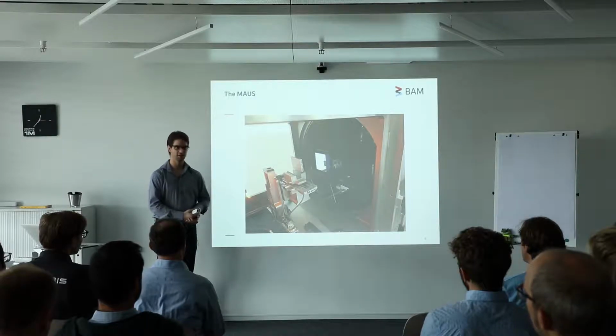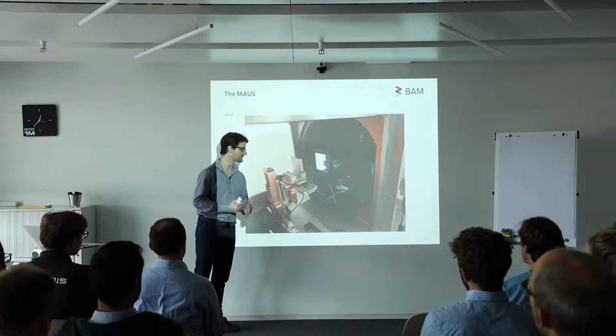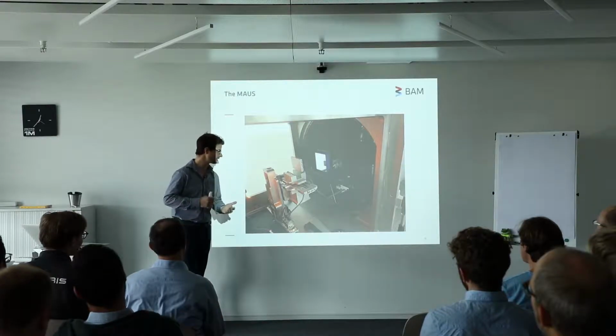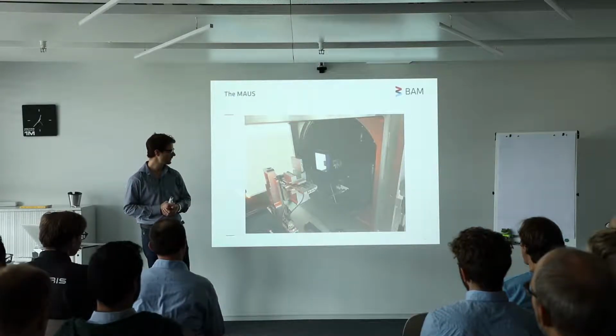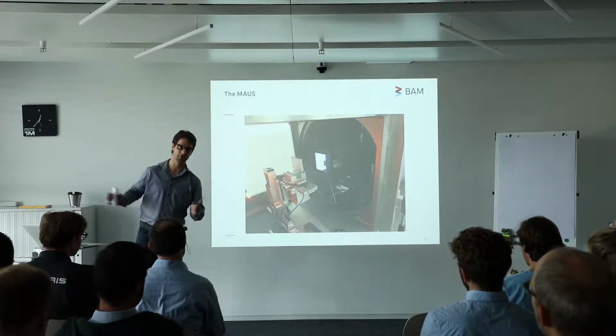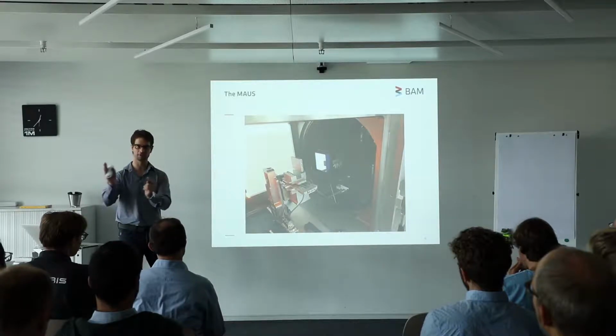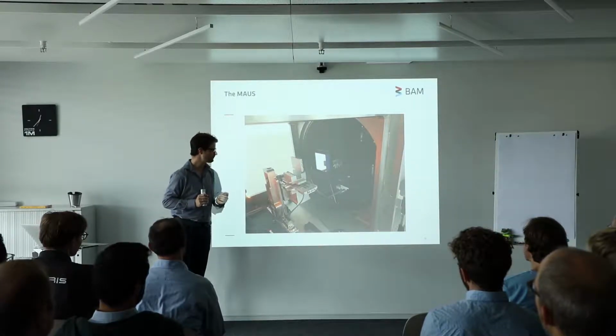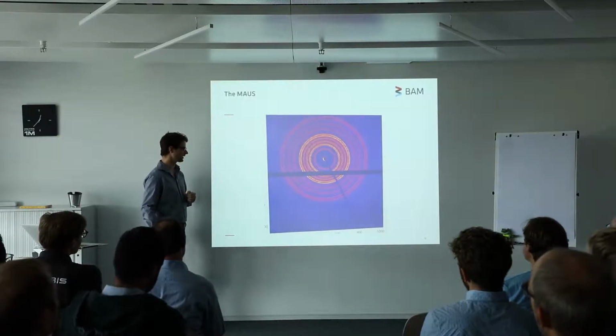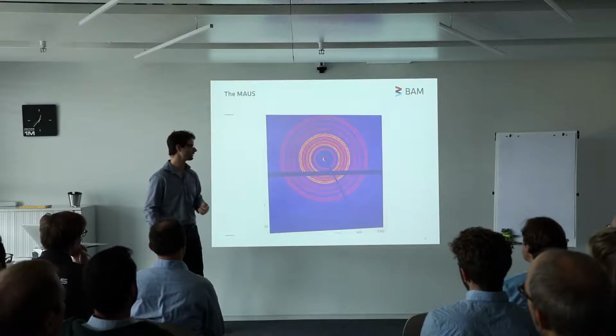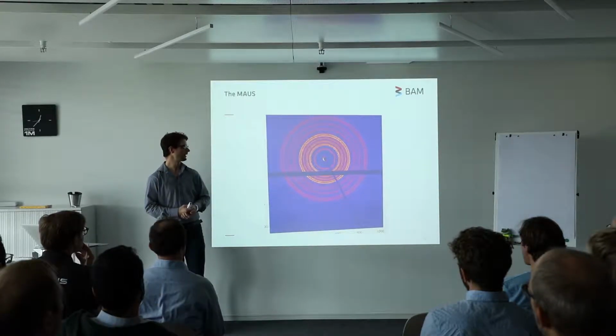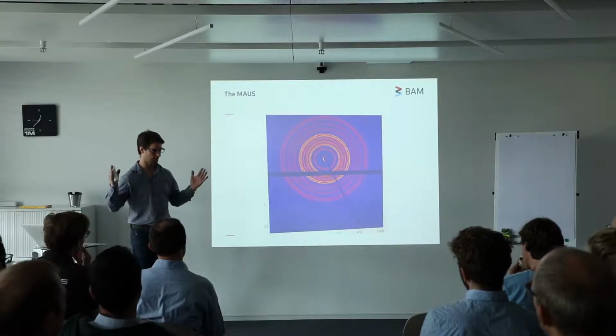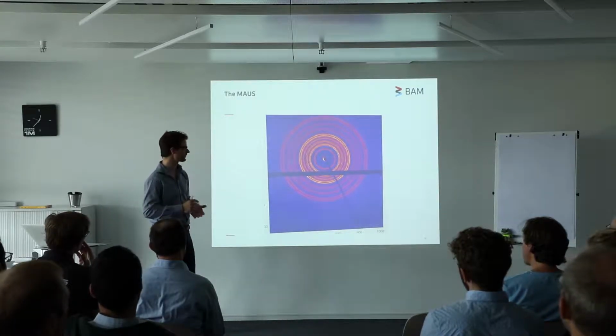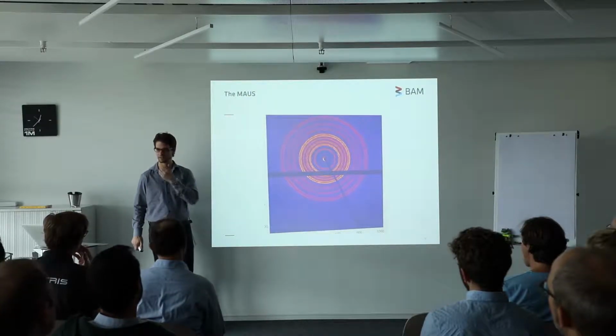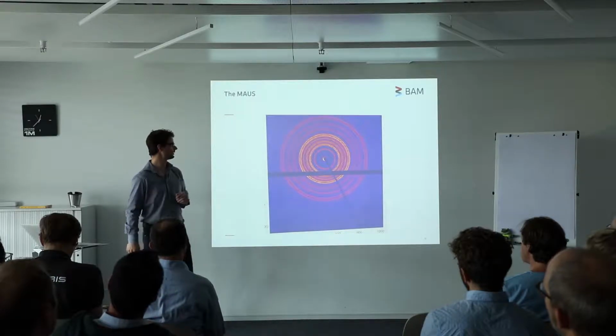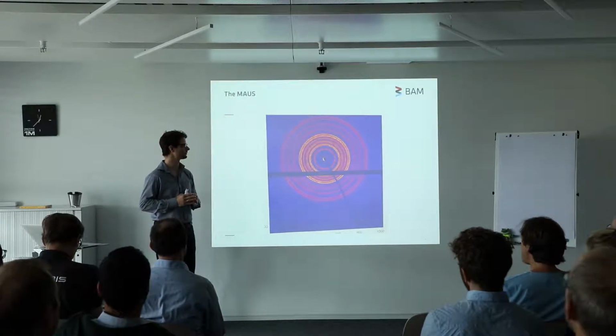One nice feature in this machine is the detector. It is a relatively small Eiger 1M. It's about this big with the detection surface. And this detector sits on a motorized platform, so we can drive it into the sample if we're not careful. We can drive it very close to the sample if we are. And this means that we can collect the wide-angle scattered region, also including the X-ray diffraction peaks. We can even, with a molybdenum source, get a Q range so wide that total scattering and PDF comes into question. But we haven't started looking at PDF just yet.